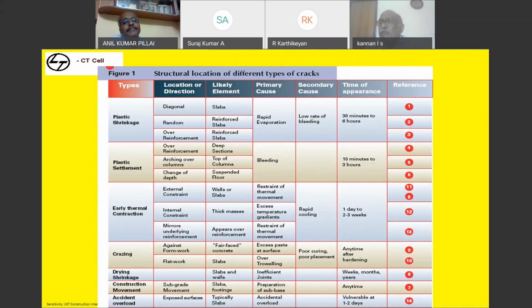If you are able to remove the column side shuttering before 24 hours, it is okay, because the heat dissipation can happen, so that the concrete doesn't have much thermal shock. Don't keep the shutter for 3 or 4 days. When you then remove it, the internal temperature may be around 65 to 70 degrees and your ambient temperature may be 30. There will be a sudden release of 30 to 35 degrees of temperature from the concrete to the external ambient, which makes the surface of the concrete crack. This thermal shock can make the concrete crack. This normally happens in thicker wall sections and where high strength concrete of M50 and above is used, especially circular columns or larger columns.